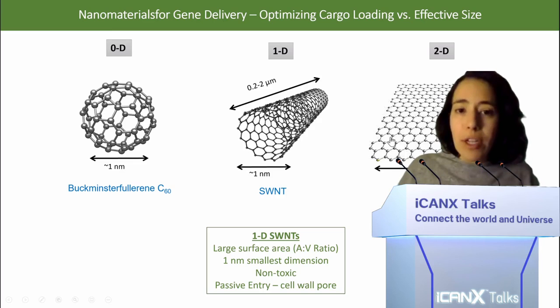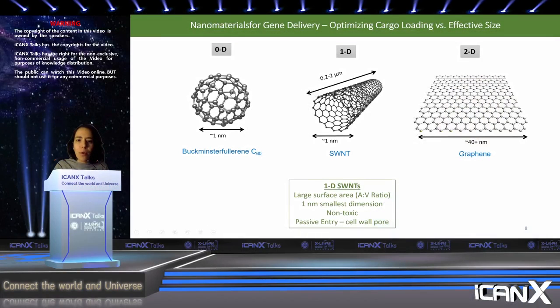So for example, 0-dimensional nanomaterials are small enough to fit through the plant cell wall, at least in theory. However, there's not a very high surface area to volume ratio onto which we can do chemistry or graft biomolecules. Conversely, 2-dimensional materials, atomically thin graphene, have a very high surface area to volume ratio, but no longer are below the size exclusion limit. We largely focus on these high aspect ratio 1-dimensional nanomaterials because they are at least in 1 dimension small enough to fit through the plant cell wall, and have an extruded first dimension that gives them a high surface area to volume ratio for chemistry and for cargo loading.